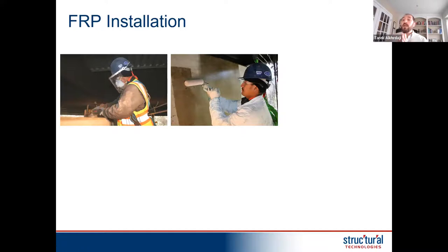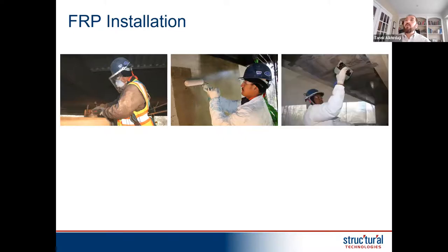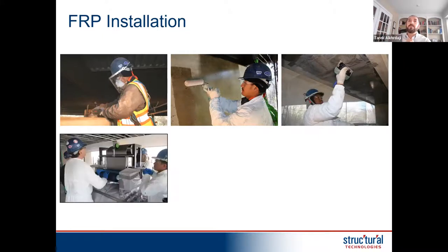First step in installing FRP is to use a layer of epoxy that is very flowable. It's almost like water consistency. The idea is to get this first layer to penetrate into the concrete, get absorbed by the concrete, and that would stiffen and strengthen the outer layer of the concrete. Then we use a next layer, which is a thicker epoxy. It's almost like peanut butter consistency. Its objective is to fill these bug holes and deformations and create a smooth surface for the concrete, because we want to get perfect bond, fully bonded into the concrete. So this allows us full penetration of the surface.